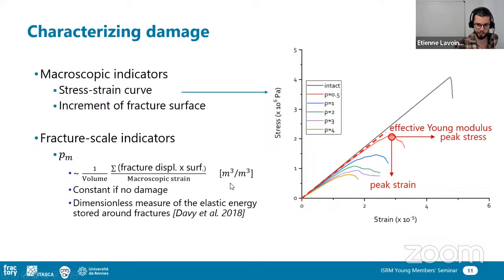Meaning that once again we obtain a dimensionless measure, and this is because if you are in the elastic regime, this is constant, because the more you apply stress or strain on your sample, the more you increase the displacement on the fracture, and this is proportional to the applied stress or strain. So this is constant, but as soon as you deviate from this constant value, you are able to say, okay, I'm creating some damage here because we are not in the elastic regime anymore.